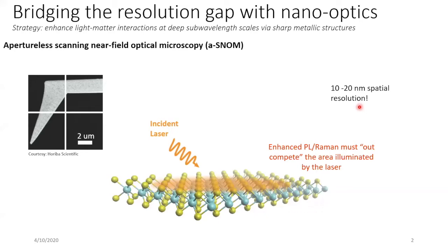Yes, we're using TERS and TEPL. These are a subset of a more broad class of near-field techniques, scanning your probe across the surface. This is contrasting with other near-field scanning techniques which are more aperture-based. The basic idea is we want to use a metalized AFM tip to locally enhance the field so we can get high resolution optical spectroscopy and microscopy of any sample of interest.